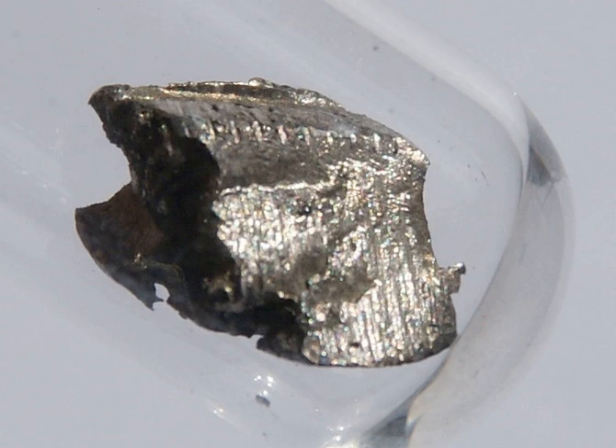The DHCP double hexagonal close-packed form beta cerium is the equilibrium structure approximately from room temperature to -150 degrees Celsius. The FCC form alpha cerium is stable below about -150 degrees Celsius. It has a density of 8.16 grams per cc. Other solid phases occurring only at high pressures are shown on the phase diagram. Both gamma and beta forms are quite stable at room temperature, although the equilibrium transformation temperature is estimated at around 75 degrees Celsius. Cerium has a variable electronic structure.